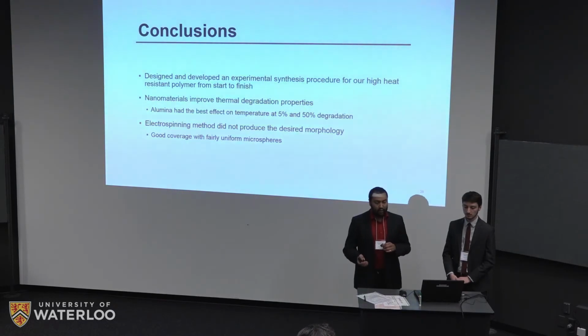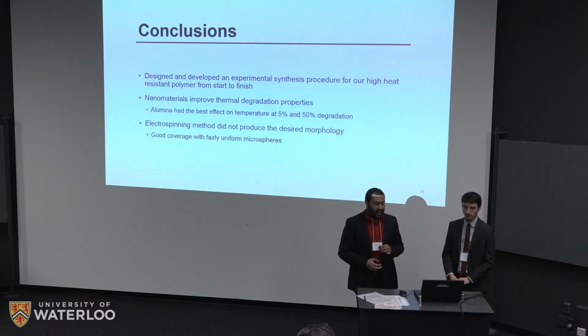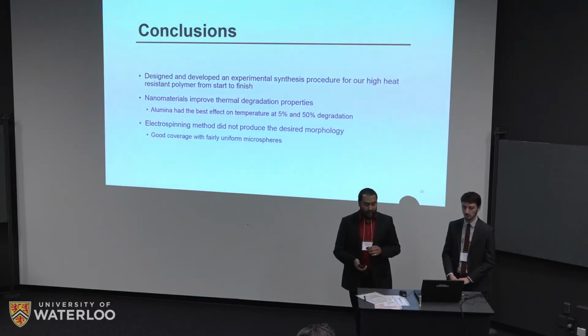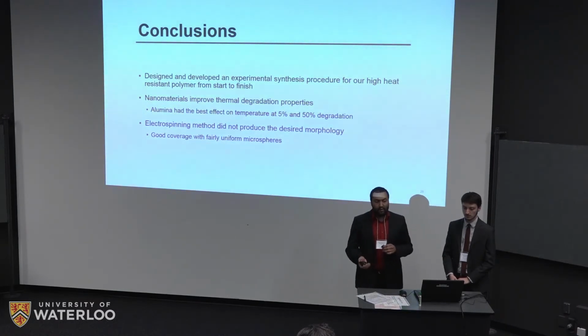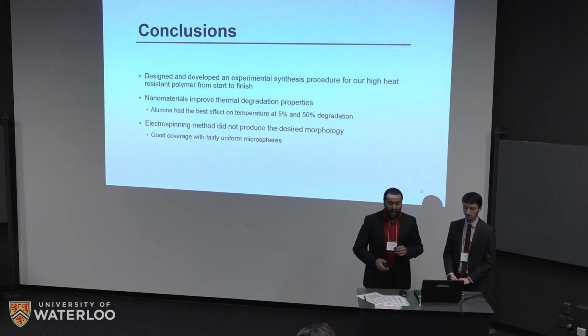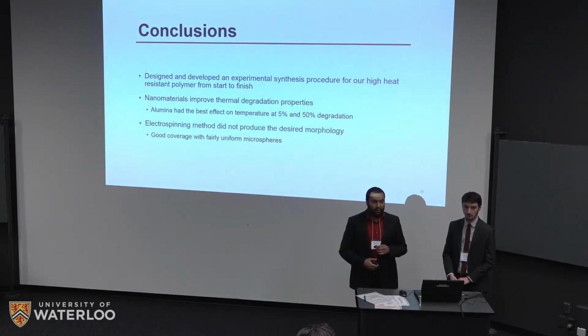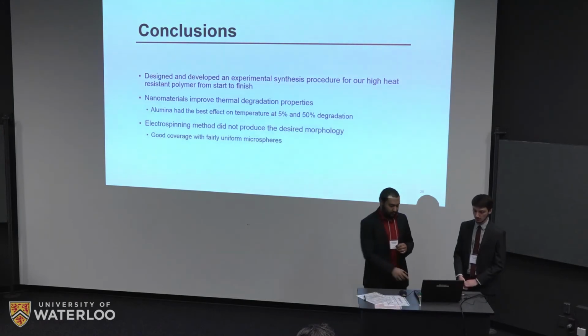And then finally, we also found that the electrospinning method that we used, given the parameters that we had, did not produce the desired morphology. But it did give us good coverage with fairly uniform microspheres, and we were able to still characterize the thermal properties and get some good data.